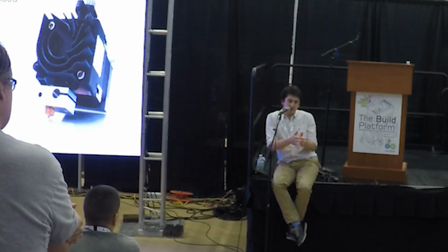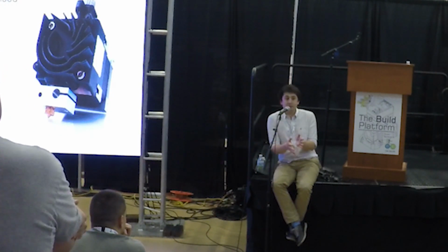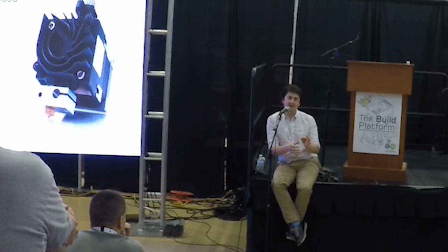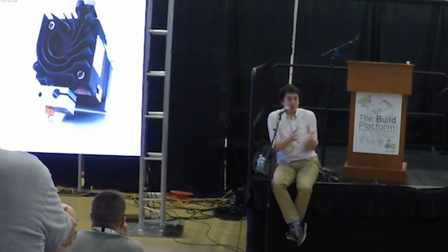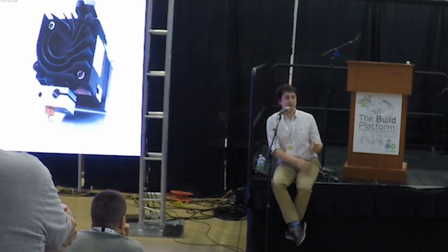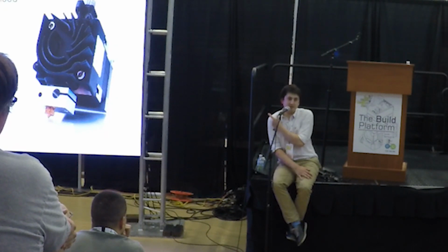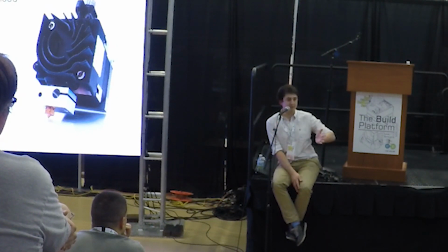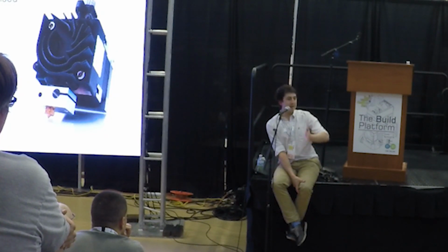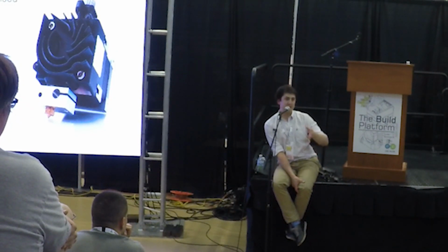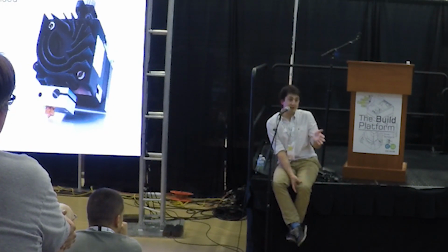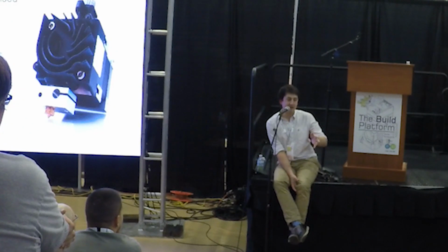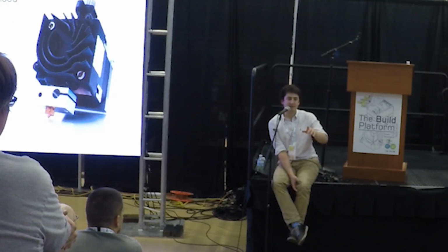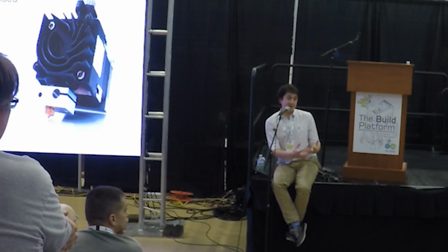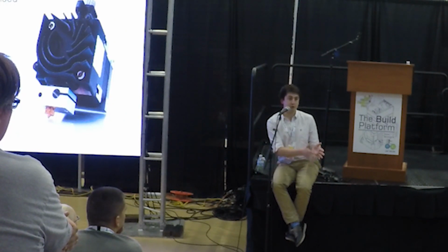These are good fans with bearings and stuff. I don't know the exact cause of failure. I think the lubricant comes up and then they fail. So for any extruder that is running these kind of consumer PC hardware fans, really your maximum temperature is 40 degrees centigrade, and that limit is not imposed by the thermal design of Hemera or anything like that. It will run in 45, 50 degrees and I'm quite happy it will still print PLA, I think. I'll fact check myself on that. But the failure mode is that the fan begins to fail with a shorter and shorter lifespan.